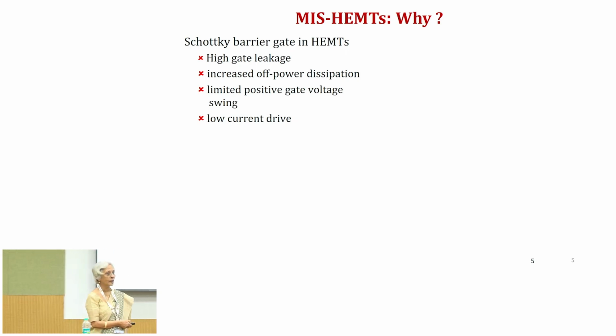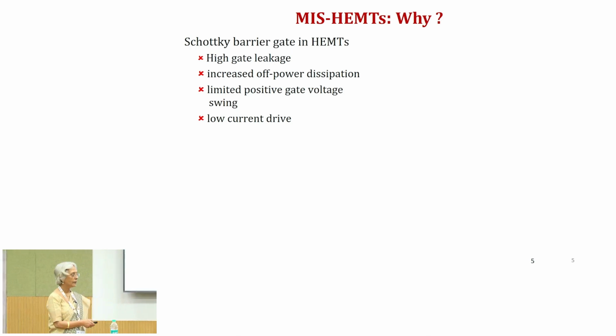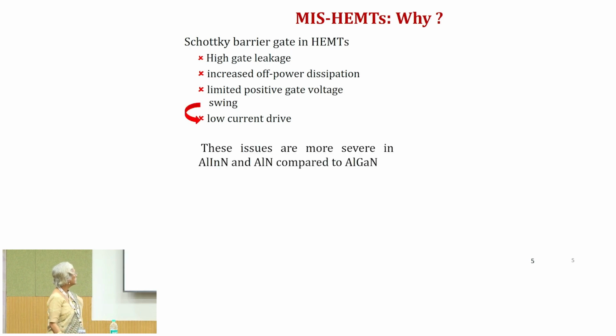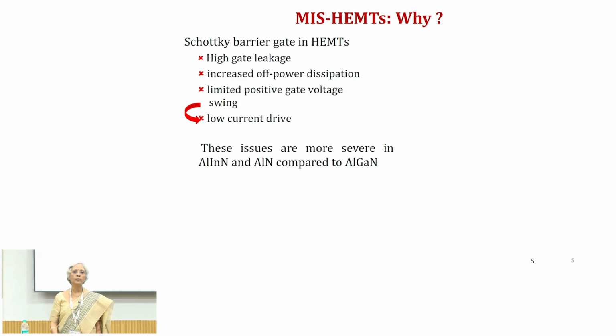So, I was telling you about the nice things about the aluminum indium nitride gallium nitride system, but there are lots of negatives as well. And these issues, particularly the limited positive gate voltage swing and high gate leakage, are much more severe in aluminum indium nitride and aluminum nitride. This comes from the inherent fact that in the aluminum indium nitride gallium nitride system, we have a much higher spontaneous polarization, and that means that the electric field in the barrier is much higher compared to the aluminum gallium nitride system.